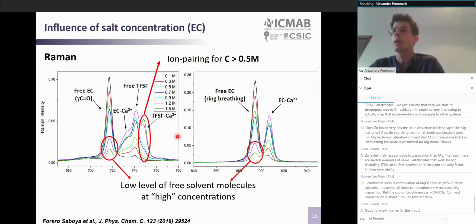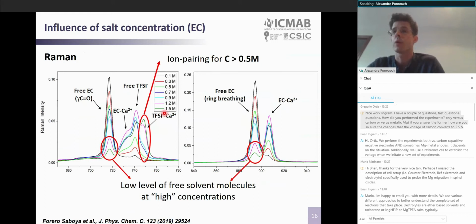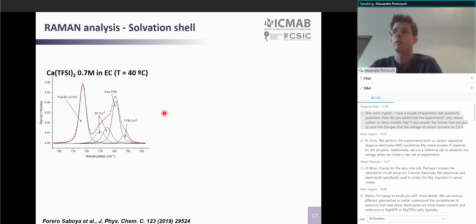And as we have more solvent molecules in the solvation shell, in the primary solvation shell for this divalent cation system, we also observed a very low amount of free solvent molecule in the electrolyte for concentration as low as 1.5 molar. So we are basically entering the realm of super concentrated electrolyte for rather low salt concentration in these systems. So those are parameters to be careful about when designing new electrolyte for divalent cation-based systems.